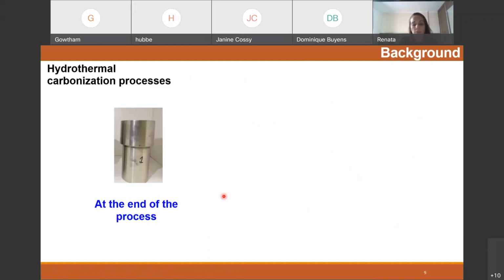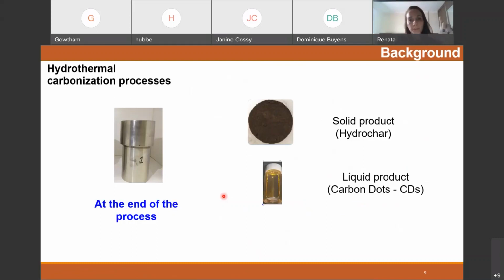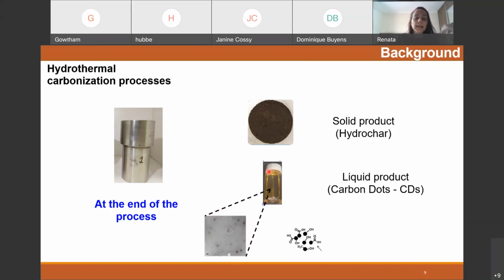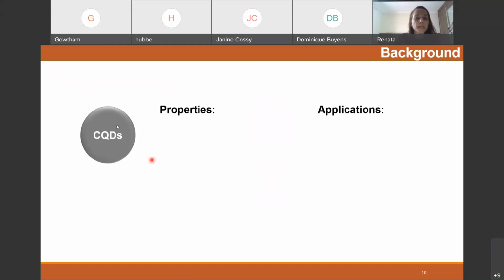At the end of the process, a solid hydrochar is obtained, and in the same process, in one pot, a liquid product is generated. This liquid product is a suspension, and it can be seen in this image. This image was obtained by electron microscope, and it is possible to observe spots in this picture that represent the presence of carbon dots in this liquid product. It's interesting to say that carbon dots have many surface groups, for example, phenol groups, amino groups, and carboxylic groups too.